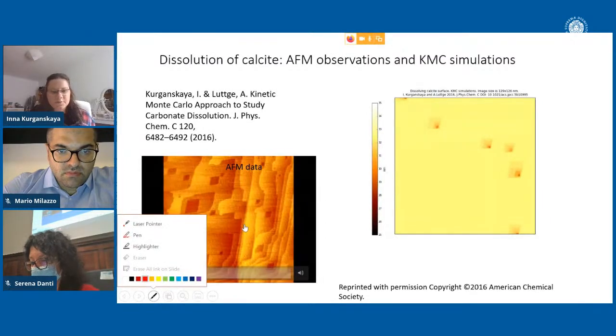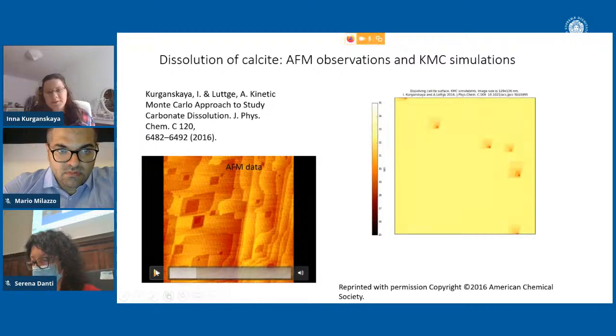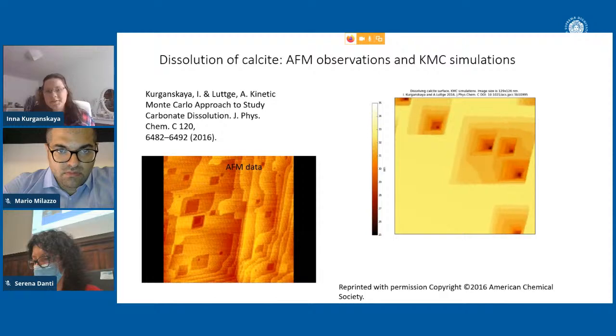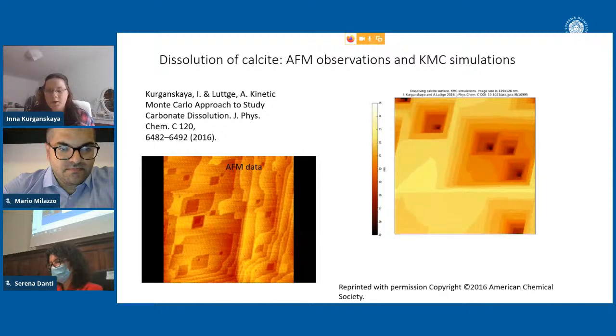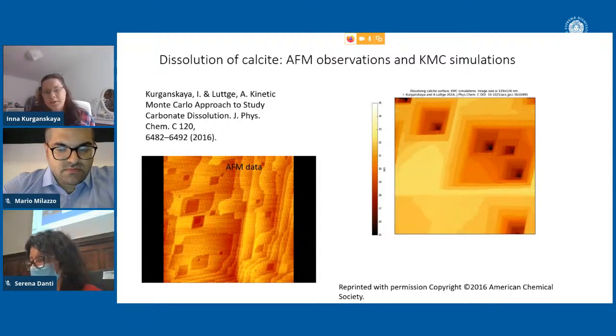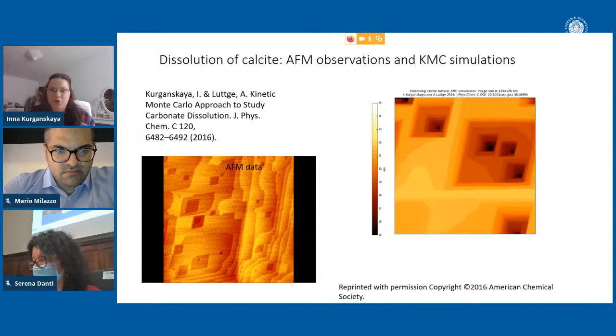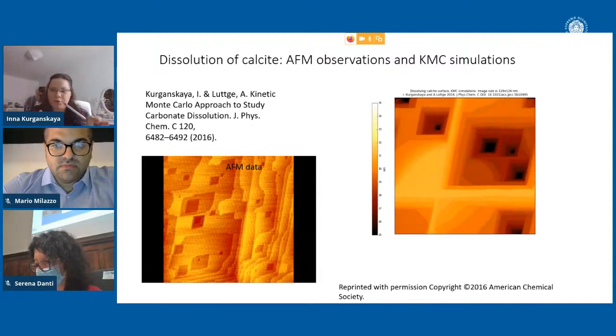So as a result, with the kinetic Monte Carlo simulation, I see surface alteration over time. So here you can see a direct comparison between atomic force microscopy measurement, this is calcium carbonate dissolving, and kinetic Monte Carlo simulations. I put together different time frames to show how calcium carbonate, mineral calcite, dissolves over time. I have some lattice defects, pretty much screw dislocations that go through the surface and work as sources of the reactive steps on the surface. So in this way, reactive surface area is generated and certain reactive sites are generated.